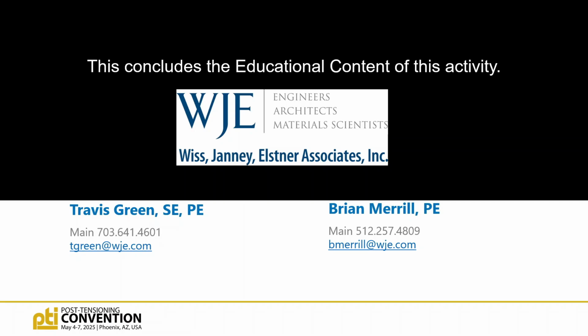So we went through and actually, when I was at TxDOT, hired WJE to go in and sample the grout and test it. And so Travis mentioned that white chalky grout that sometimes forms in some of those earlier bridges. And it doesn't have the compressive strength you'd like it to have, but it actually still has a very high pH. And so we actually did some compatibility testing of that high pH but chalkier grout and found it was still compatible with a newer grout at similar pH.